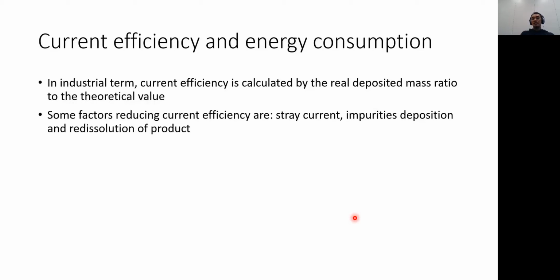Some factors that reduce current efficiency are stray current or bad connection in the bus bar in the process, impurities deposition, and also redissolution of products. I have touched on impurities deposition. If we use that fraction of current to deposit copper, it also reduces the current efficiency. In the case of silver electrorefining, redissolution of product severely affects the current efficiency. As we know, in the silver process, silver accumulates on the bottom of the cell. And since the electrolyte has nitric acid, it will dissolve the fine product silver.